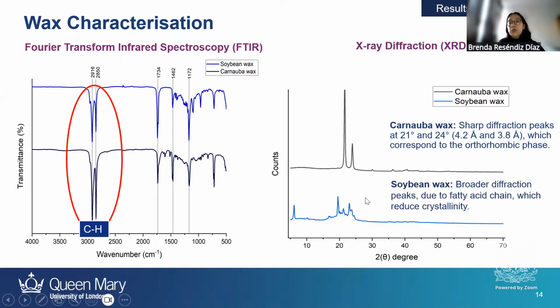But when we go to the X-ray diffraction, which tells you about the crystal morphology, here Carnauba wax has two diffraction peaks at 21 and 24, or 4.2 Angstrom and 3.8 Angstrom, which correspond to the orthorhombic phase. This orthorhombic phase relates to a specific crystal structure where all the axes are of different length, but they are perpendicular. So this is very common in waxes.